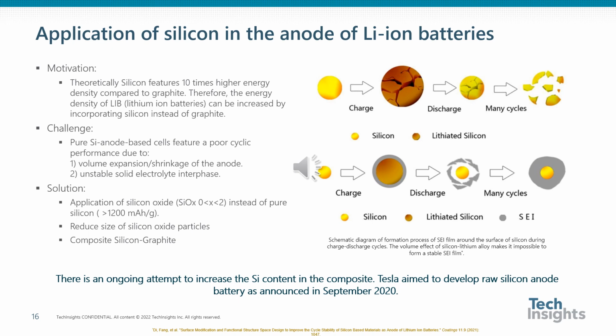Before characterization of these three key products, let's have an overview on the motivation of application of silicon in the anode of lithium-ion batteries in this slide. The most used anode material for lithium-ion batteries is graphite, which has a specific capacity of 372 mAh per gram. However, the energy density of the battery can be improved with incorporation of silicon instead of graphite. Silicon features a high theoretical specific capacity of 4200 mAh per gram, which is more than 10 times higher than that of the traditional graphite anode.